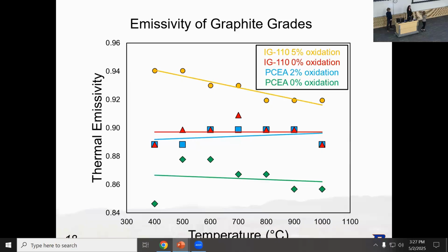The same trend was true for the PCEA, which is the 2% in blue and the 0% in green. But the trend we did not expect is that the fine-grained grades actually had higher emissivity than the coarse-grained. Our initial thoughts about why that might be is that the starting carbon source and the proprietary blend of filler versus binder particles may actually have more of a role in emissivity than the microstructure and grain size does.